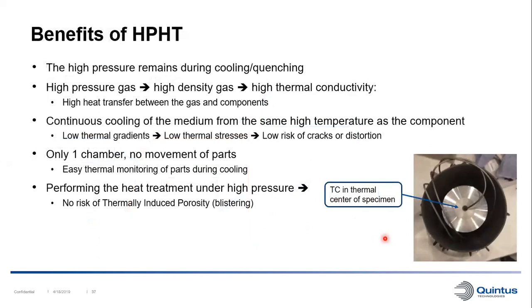Some of the benefits with high pressure heat treatment. One thing to notice is that the high pressure in the process remains during the cooling and quenching. And since we have this high pressure gas, we also have a very high density in the gas. And this gives us a very high thermal conductivity in the pressure medium, and a very high heat transfer between the components and the process medium. And this is very good when it comes to heat treatment.